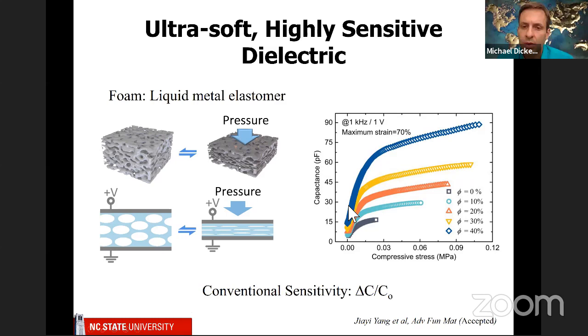So you get a really good initial capacitance change. These numbers here refer to the percentage of liquid metal that's in the silicone. So the more that you add, the more sensitive it gets. And the beauty of this is it gets more sensitive without getting stiffer. So by adding more liquid metal, you get this blue data where you get really big changes in capacitance.